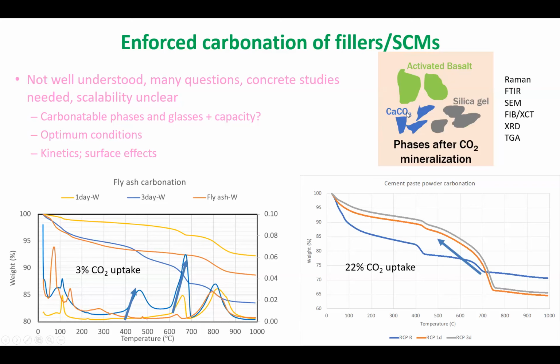Maybe, maybe not. On the other hand, this is a recycled cement paste. By recycled cement paste, I mean you mix cement and water, okay? And then once it hardens, you grind it to some sort of a 15, 20 D50, and then you expose it to CO2.